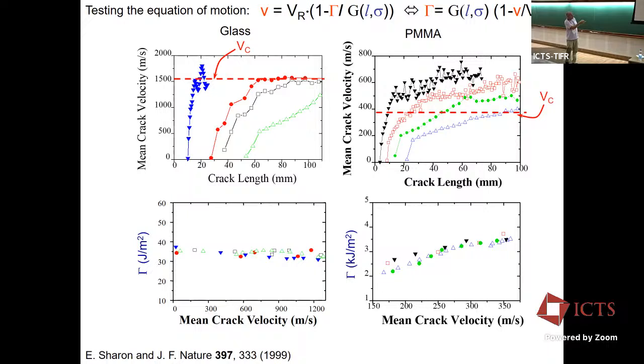We know what the Rayleigh wave speed is, we measure the instantaneous V, we measure the instantaneous L, we know what this function is, we can calculate it. And using that, we collapse all of these measurements to well-defined curves. In glass, it's fairly constant, like as advertised. And in plexiglass, the curve is increasing slowly with the velocity. But again, that's fine too. Okay, so can we go home?